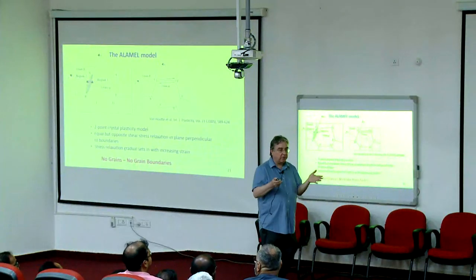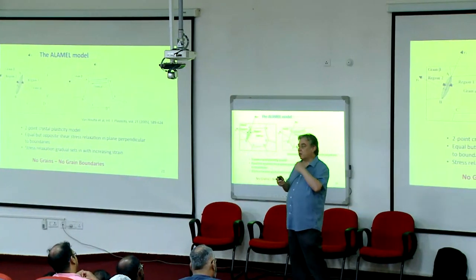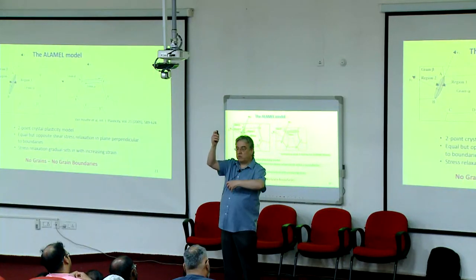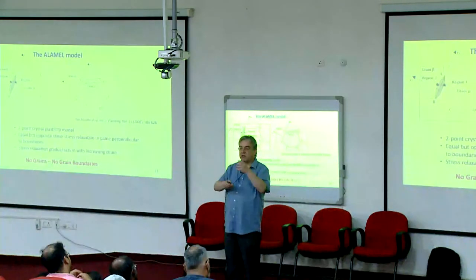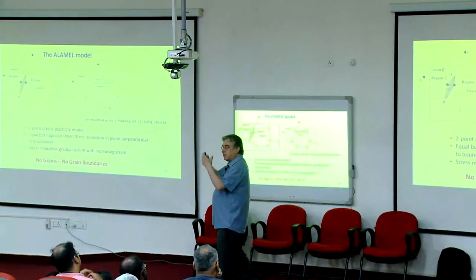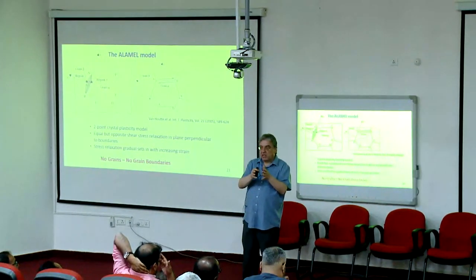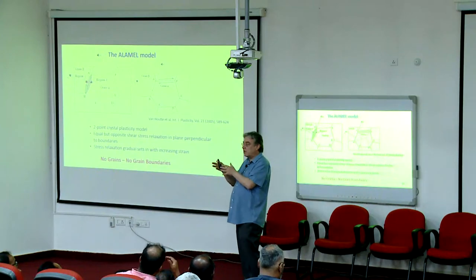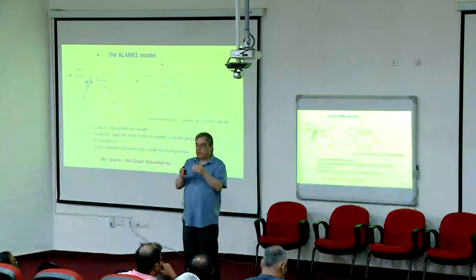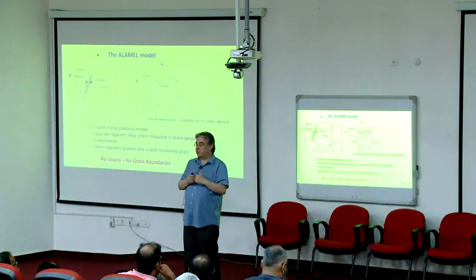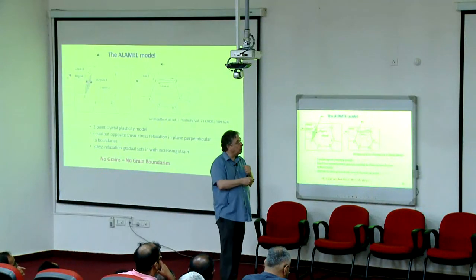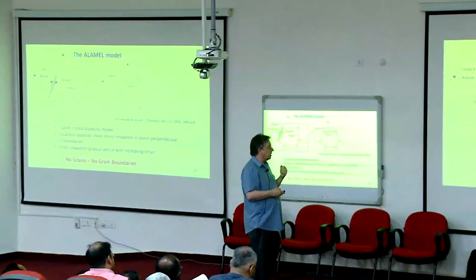And this is not continuum. There is a finite number of crystal planes and crystal directions, slip systems, we call them, that can accommodate plastic deformation. So how do you combine this macroscopic world of rather arbitrary plastic deformation in all directions, the way you'd like, with the atomic world, the crystallographic world, the rather quantized way of strain? These two worlds have to be brought into contact with each other, and one way of doing this is by crystal plasticity models.